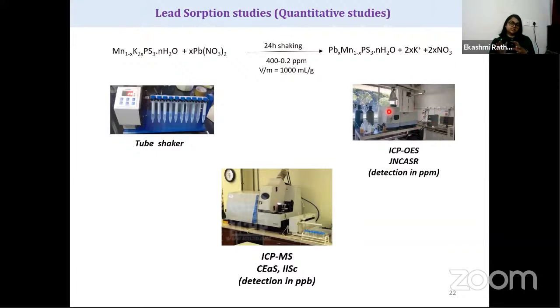What happens in this technique is that the liquid samples will be ion sprayed with the use of plasma, and these elements will separate out, and with the help of a spectroscopic lamp, each element will show peaks at different wavelengths. So it will help us to detect those heavy metal ions which are present. ICP-OES helps us with detection at the parts per million level. And for the parts per billion level, we have used an ICP machine attached with a mass spectrometer.